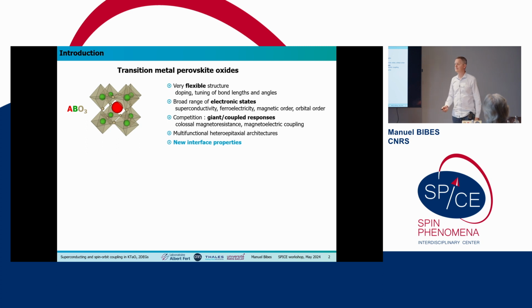Okay, so I think there were a few talks about complex oxides already, in particular from Javier Villegas. But just in a nutshell, we work with these oxide perovskites, which have this general formula. And as you perhaps know, they have a very flexible structure. You can really have many different compounds with almost the same crystal structure, which means that you can combine them into heterostructures with very clean interfaces. And typically at the interfaces, quite often you are going to find some new physics.